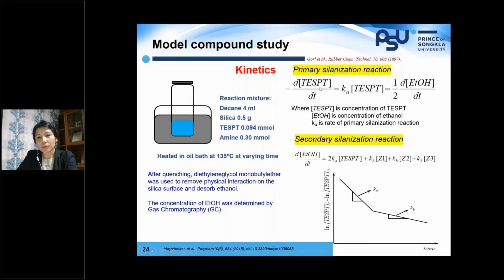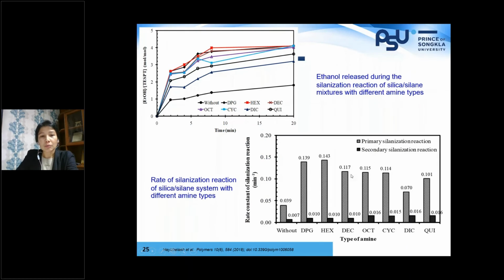So 1 molecule of TESPT releases 2 moles of ethanol. By using this equation, this primary silanization and secondary silanization, we can obtain the rate constant of those reactions. So if we see the concentration of ethanol per concentration of TESPT, by simply looking at this plot, we see already the effect of amine in the model compounds.